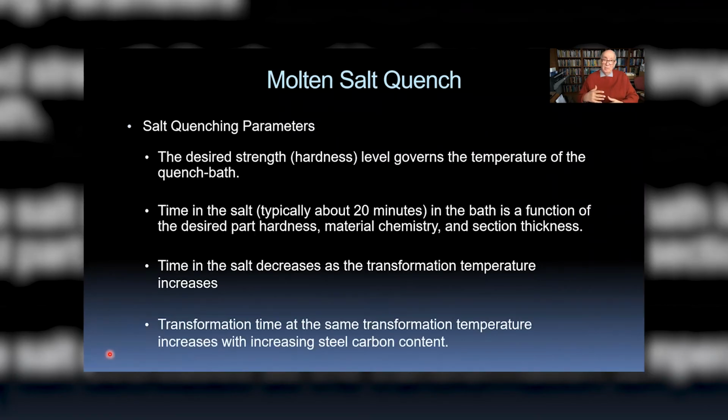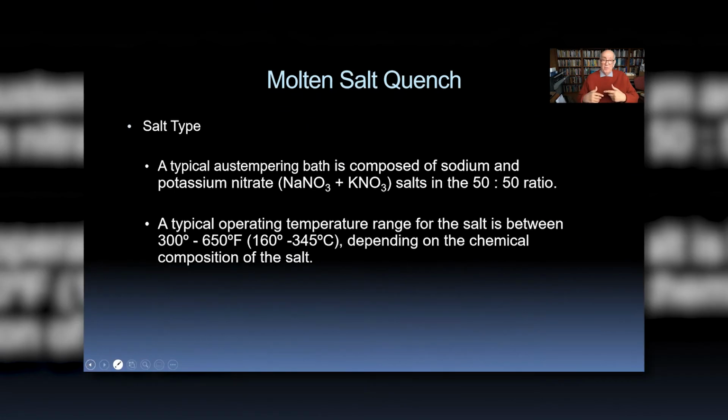So I was going to say, let me back up for a second, Doug. To summarize this, when we're trying to put the brakes on, as we're rapidly cooling down, missing the nose of the transformation curve, we want to fall into this bainitic region. And in order to do so, we need to stay above that martensite start temperature, which for many steels is in the 400 to 450 degree Fahrenheit range.